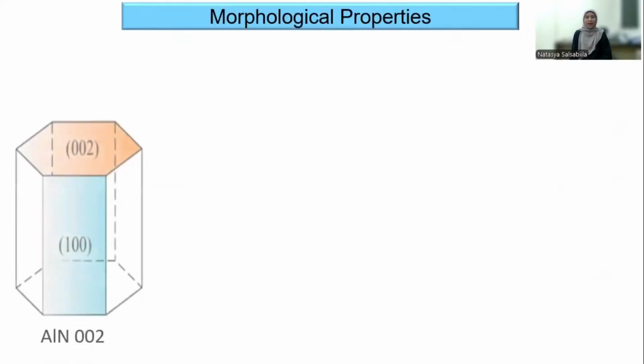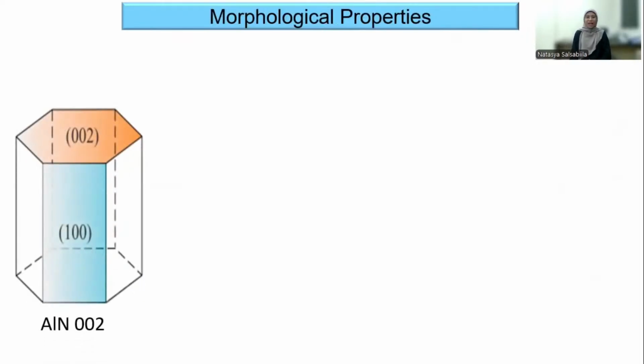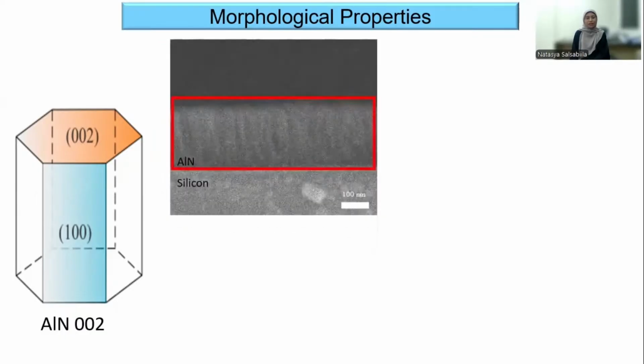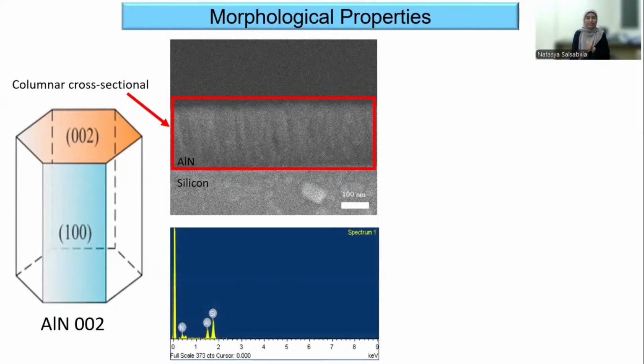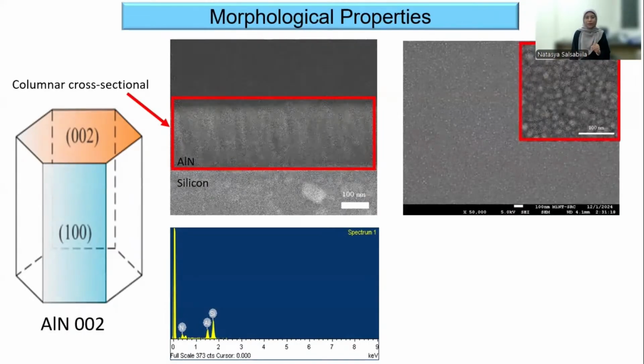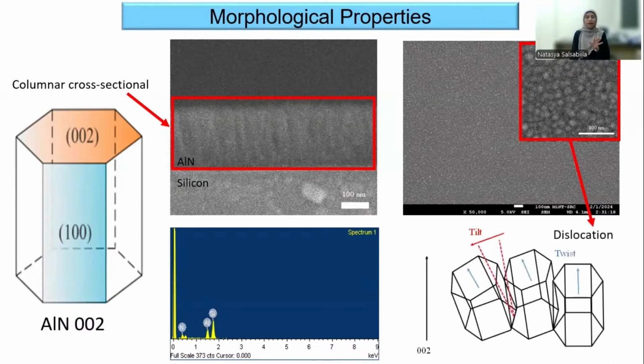Now, we have the morphological properties of the AlN. AlN with 002 orientation has a columnar structure, as we can see from the cross-section image. Also, to confirm that our film really consists of AlN material, we have the EDX results here. And it is clearly obtained that our film consists of aluminum and nitrogen atoms, with silicon as the wafer. If we see from the top view, the morphology of AlN 002 is a hexagon-like structure with a few dislocations that occur and are related to the previous XRD results.